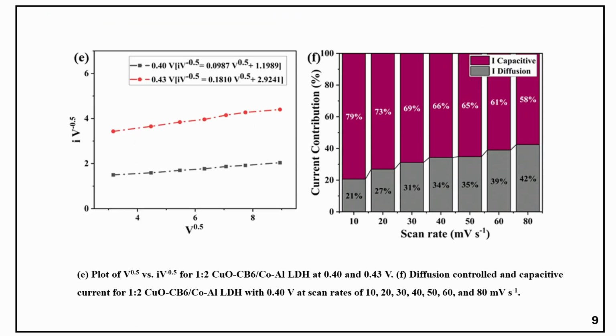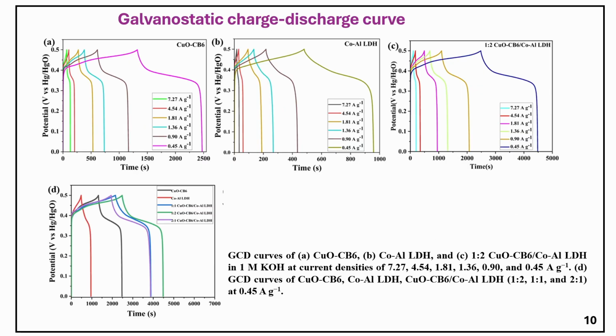Next, coming to Dunn's approach. Dunn's approach was used to plot v^0.5 versus i/v^0.5 for the 1:2 nanocomposite at potentials of 0.4 and 0.43 volt to identify the contributions from diffusion-controlled current and capacitive current. The data also identified that as the scan rate increased, the diffusion-controlled current for the 1:2 nanocomposite also increased from 21% to 42%.